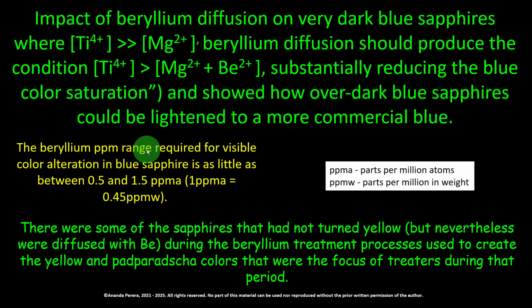The beryllium ppm range. ppm means parts per million. ppma means parts per million atoms. ppmw means parts per million in weight. These are the two units we are measuring with the LA-ICP-MS system. The beryllium ppm range required for visible color alteration in blue sapphire is as little as between 0.5 and 1.5 ppm. Parts per million atoms, it should be 0.5 or 1.5. There were some of the sapphires that had not turned yellow, but nevertheless were diffused with beryllium during the beryllium treatment processes used to create the yellow and Padparadscha colors that were the focus of treaters during that period.